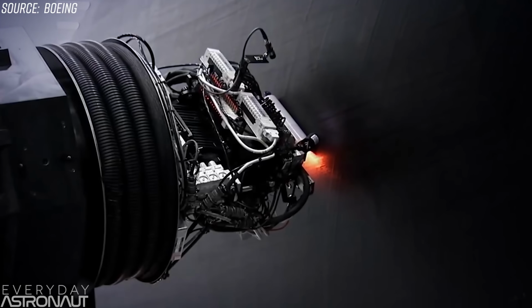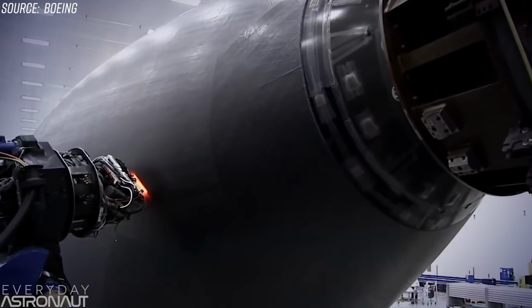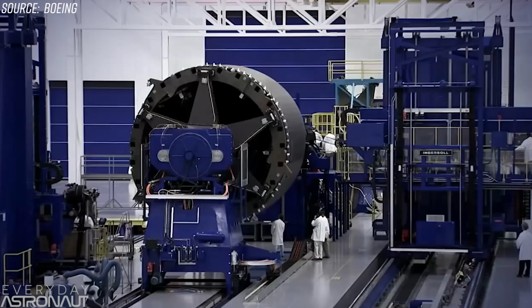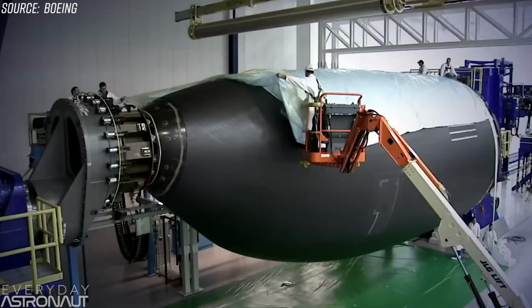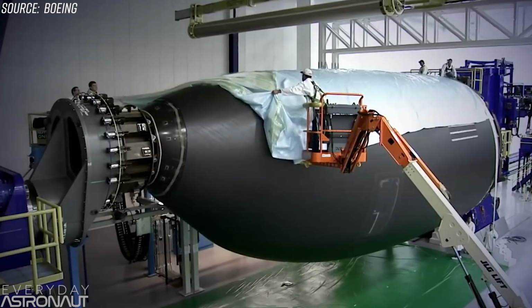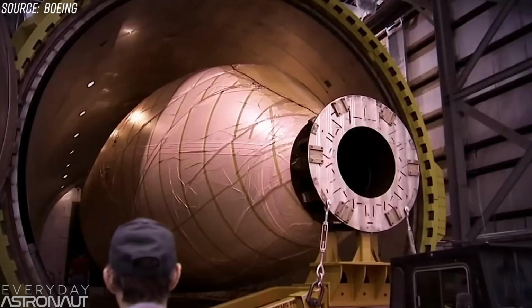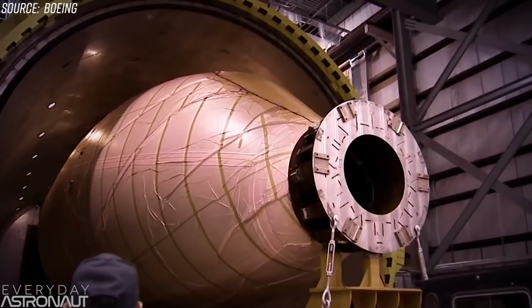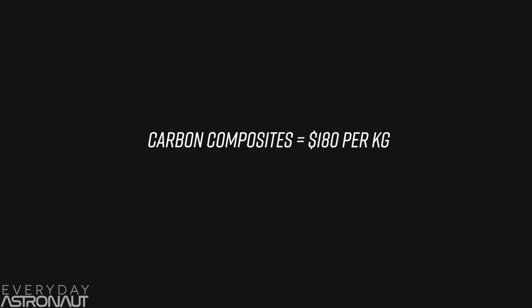Now the last two things we need to talk about are probably why SpaceX suddenly spun on their heels and totally ditched carbon composites. And that's time and money. With carbon composites, you need to cut the fabric, impregnate it with high-strength resin, which can be pretty difficult to do, and then make 60 to 120 layers. There's also approximately a 35% scrap rate of the material too, which can make carbon composites really expensive. After all, the advanced carbon composites cost about $180 per kilogram by the time you factor in the scrap material.